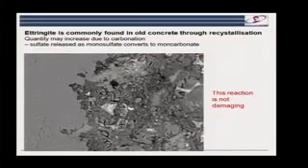These cracks are again an artifact of drying, because the water content of ettringite is quite high, and as with CSH, as we dry it out, it loses water, it shrinks. So these cracks are just an artifact of the fact we dried something out. A lot of people are saying, okay, if you see these packets of ettringite like this, this is a sign of degradation. Again, sorry to keep disagreeing with what people write, but it's not a sign of degradation.